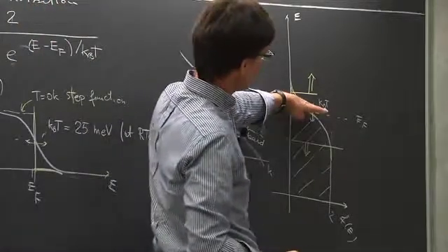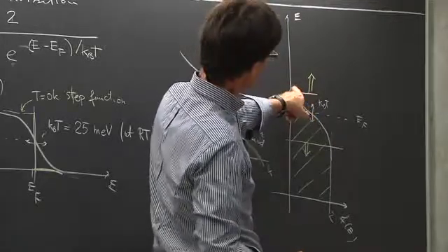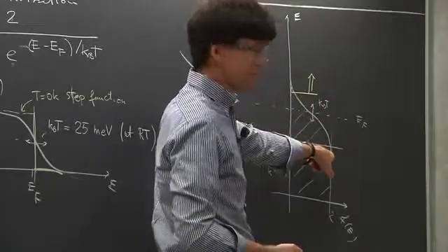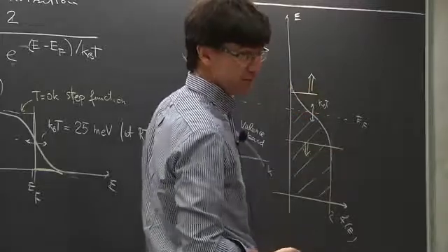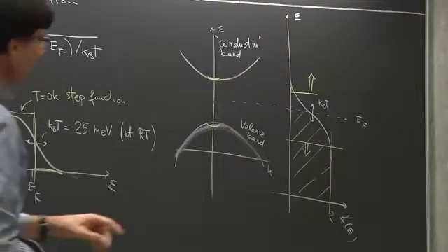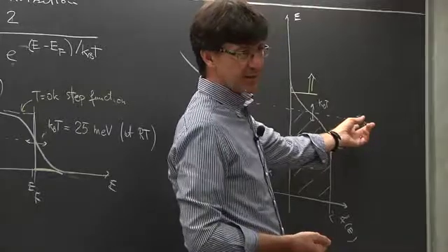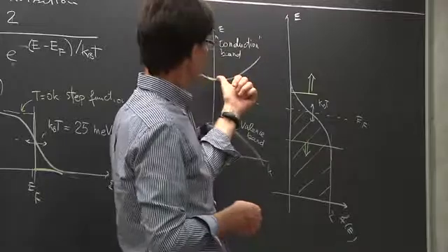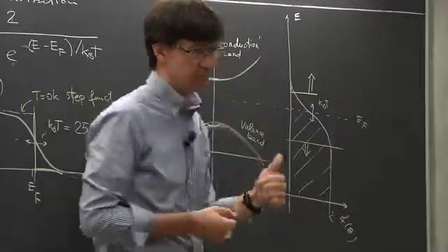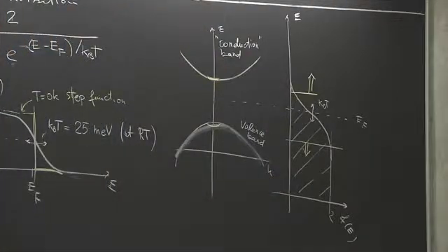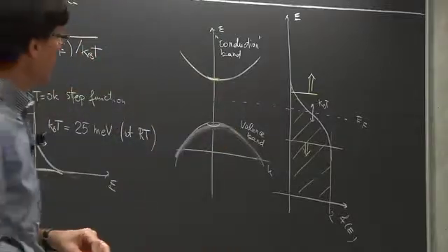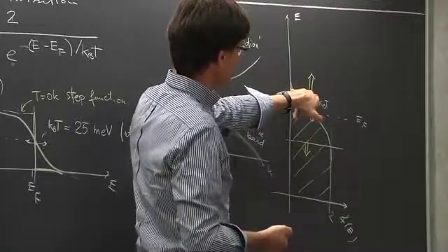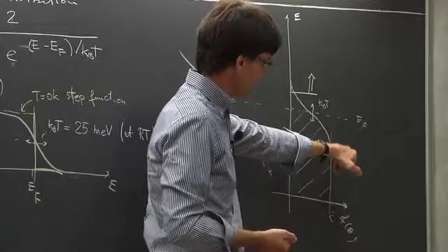Now, clearly, if I move the position of the Fermi level upwards, I will increase the occupation number here and decrease it below. Similarly, if I move it downwards, I will increase the occupation here and decrease the number of electrons there. So the consequence of this argument is that the position of the Fermi level is actually not arbitrary. I will place it exactly at the point which makes the number of electrons here exactly equal to the number of electrons that I removed from there. This is the criterion I will use to place the exact position of the Fermi energy, so that this small number equals the integral of the small number below.